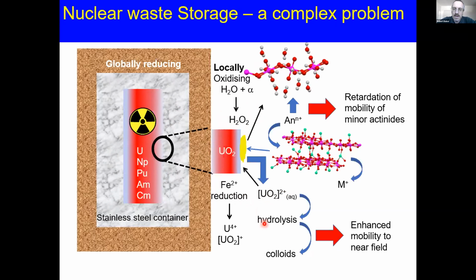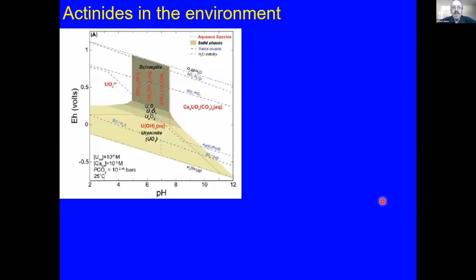Maybe these can move via hydrolysis to form colloids. There are problems with the stainless steel, which won't be stainless over these periods of time and generate iron sites for reduction. Or we could have maybe the incorporation of these radionuclides into new phases that are formed on the surface of spent nuclear fuels. So this can either retard or enhance mobility to the environment. So it's a really complicated situation.